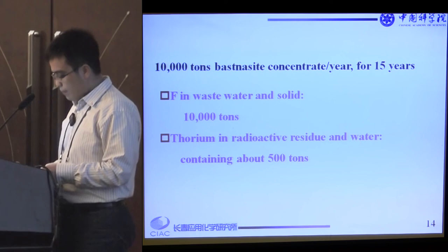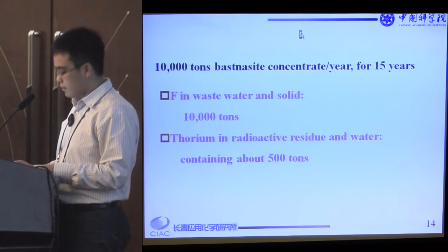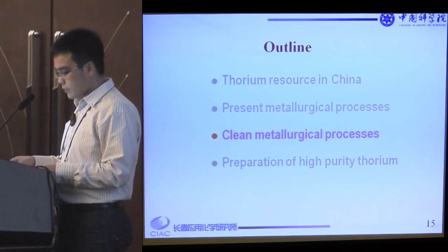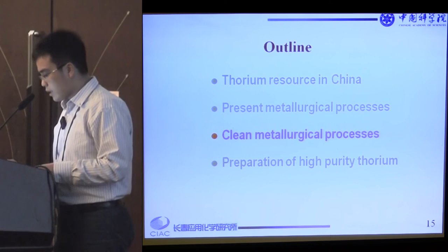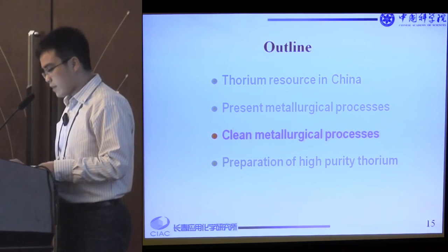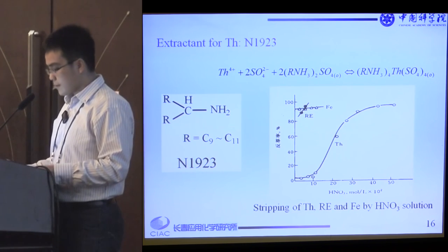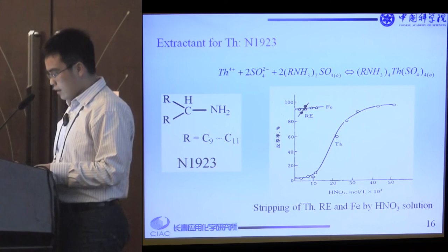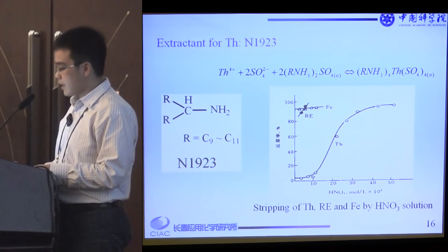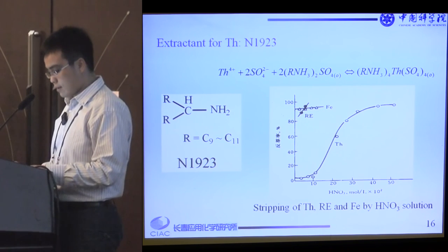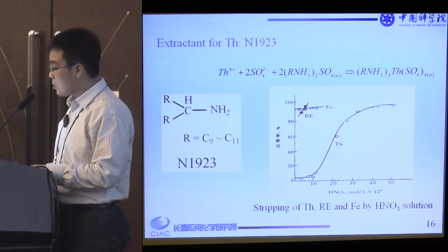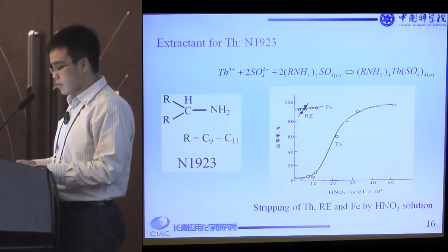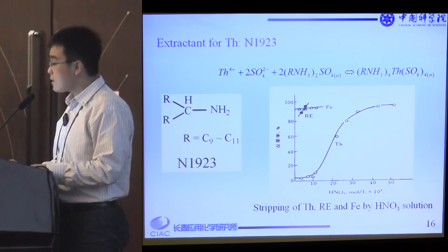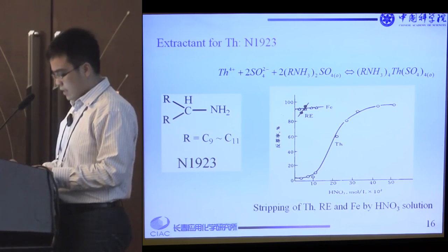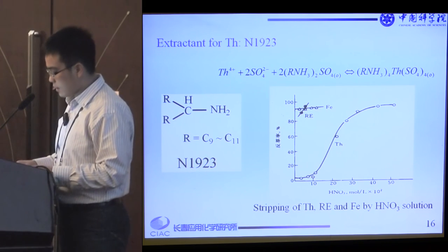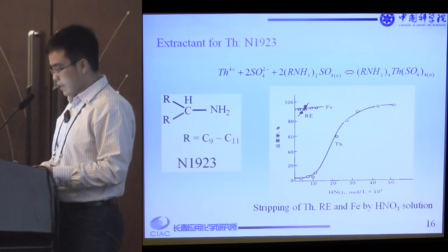Both present metallurgical processes in Baotou and Sichuan show disadvantages. Based on previous work, we developed two new clean metallurgical processes for Baotou and Sichuan ores. Study demonstrated that the primary amine extractant N1923 has several advantages, including easy preparation, low solubility in water, high separation factors between rare earths and thorium, and especially the ability of easier stripping. Hence, it is an excellent extractant for extracting thorium from sulfuric acid solution.